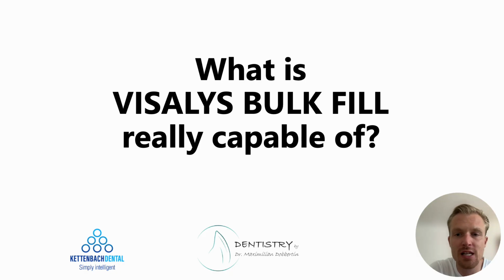A key feature of Visalys Bulk Fill is its very low water absorption. This property significantly contributes to the long-term stability of the restoration, as it reduces the risk of marginal changes and supports the integrity of the filling over time. Combined with high abrasion resistance, this creates a reliable foundation for durable posterior restorations. Visalys Bulk Fill enables fast and safe single-layer application of up to 4 mm. This reduces treatment steps and streamlines workflows.